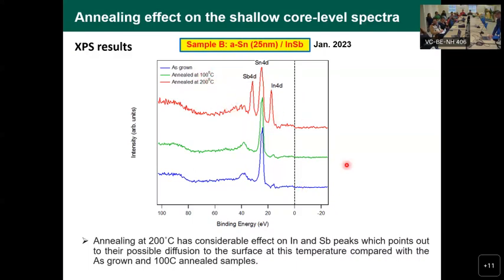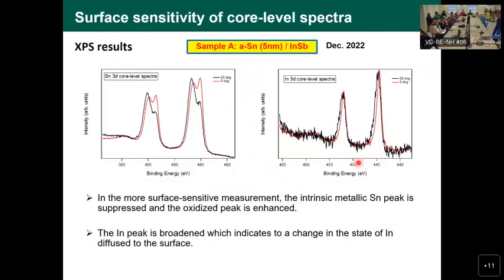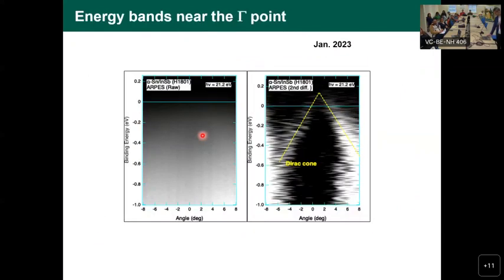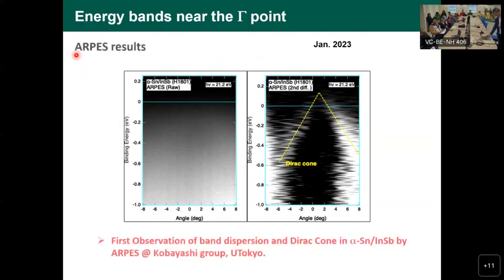This is near the Fermi level, and also we investigated deep inside the core level. So we see some shift towards here, probably higher or lower binding energy, it depends how you see it, the angle. So the change in the structure of the surface and so on. So this is very important information regarding the potential applications of these materials. We have a lot to do there. This project has just started. We started last December. And I hope we can proceed in this project as well.